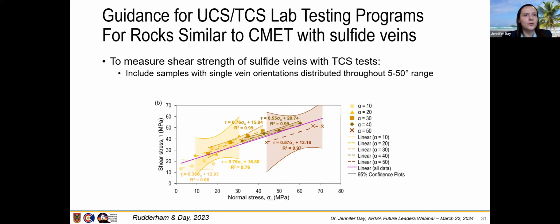Another useful result from this work is we were able to provide some guidance for UCS or TCS lab testing programs for rocks that are similar to the CMET with sulfide veins. So if you're wanting to measure the shear strength of sulfide veins with triaxial tests, this data suggests that it would be good to include samples with single vein orientations distributed throughout the 5 to 50 degree range.